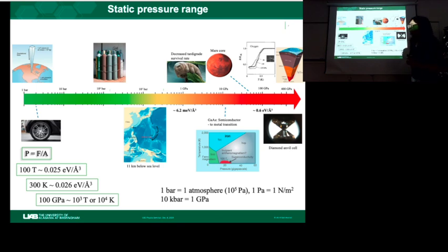Yes. So how do you compare temperature with density of energy? Well, if you convert the energy with the temperature, here it is kind of equivalent to how much change there is in the volume. So when you change the temperature, this is just the equivalent. It's not a direct translation in energy. So 100 GPa is typical for around here, close to 1 electron volt per angstrom cube. So we are counting how much you reduce the volume and translate that into energy.